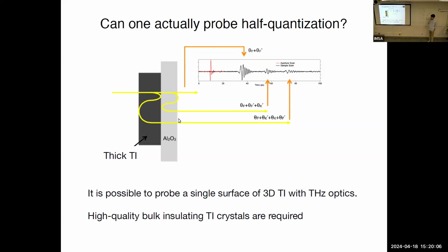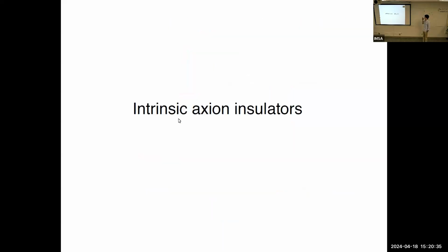But this is very challenging, because it's hard to grow thick crystals. Sometimes it's even hard to grow thin films which are 10 or 20 nanometers. In this case, it's going to be half a millimeter. So there is an experimental challenge, but in principle those two could be distinguished, and if they are, then we can see a direct showcase of this notion of half quantization on the surfaces.